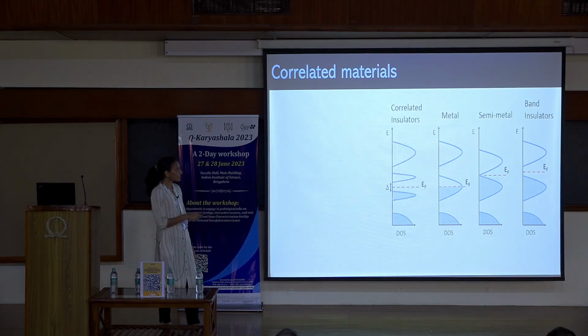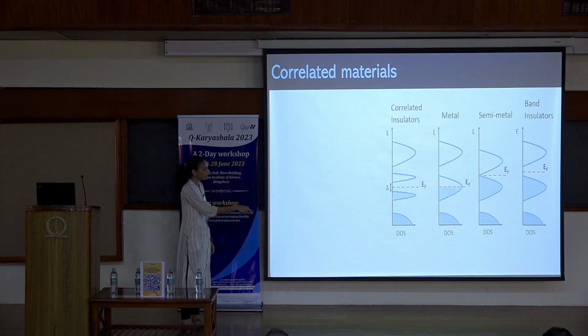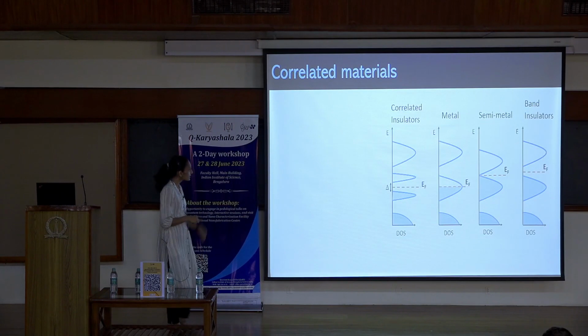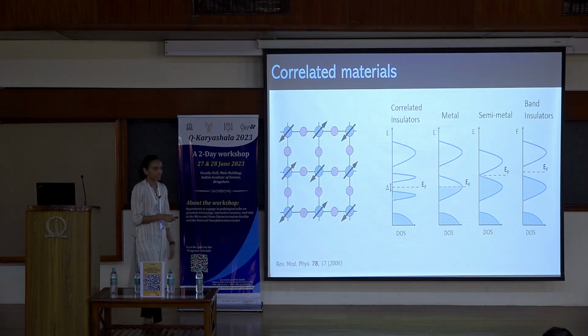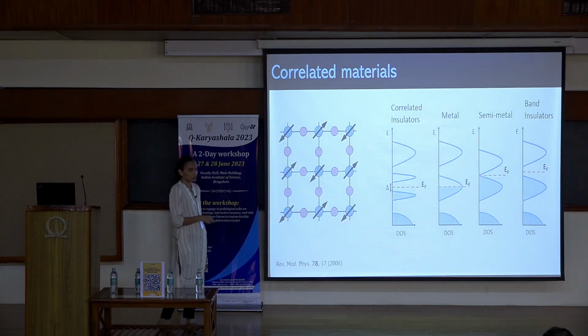But you can have a situation where you have correlated insulators. Because of correlations, this particular band now splits into two, and you can have this band gap which is present at half filling. So this half filled structure now separates into two, and your Fermi level lies inside a gap. You would normally think that it's lying inside this particular band and it should be a metal, but at half filling it turns out to be an insulator. So these are called correlated insulators. They have a lot of applications in superconductivity, and a wide variety of materials show this.